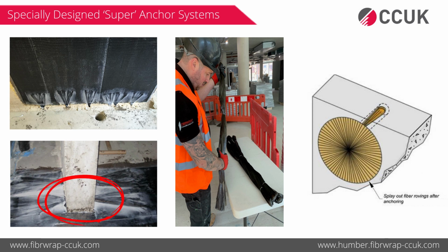Picture 2 is basically a slab strengthening example, which we strengthened for hogging moments. There was a column in the way, so what we did was drill a hole through that column, use these bigger anchors, pass them through that drilled hole, and then splay them on both sides like a dovetail. After curing, it becomes one unit, acting as a tie, which will transfer force from one side to another side. That's how these anchors are used. This is the correct way to do strengthening on top of the slab, or hogging moment strengthening, because we've got a continuous top reinforcement in that location. A similar detail is shown in picture 1, but that's a vertical element. We are strengthening a shear wall there, and the obstruction there is coming from the slab.